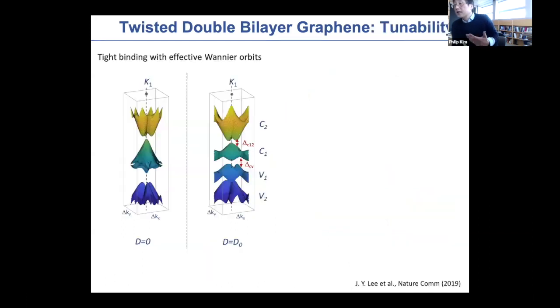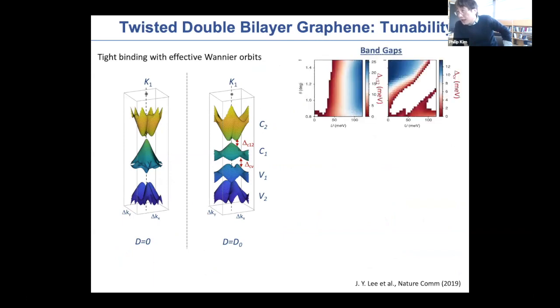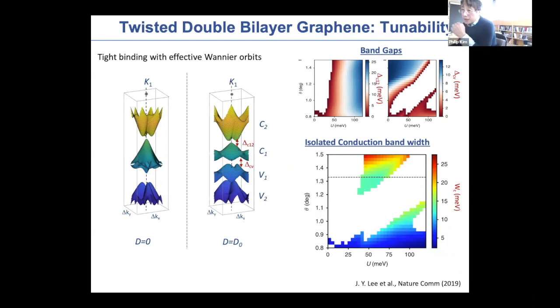Now, this simple idea was in fact taken to a more serious calculation, including both the displacement field and all the layer couplings, and this was done by Ashvin's group. Then the conclusion is the following. If you have around a 1.2 degree to 1.3 or 1.4 degrees twisting angle, by applying the displacement field, creating an imbalance of energies between these two Bernal stacked bilayers, which in this case is controlled by the parameter U, you can isolate a separate band whose bandwidth is in fact controlled by this U. So somewhere around these regions of the displacement field and the angle, you should be able to get a reasonably well isolated band with a bandwidth as small as tens of millielectron volts. So that's basically the idea behind this twisted double bilayer.